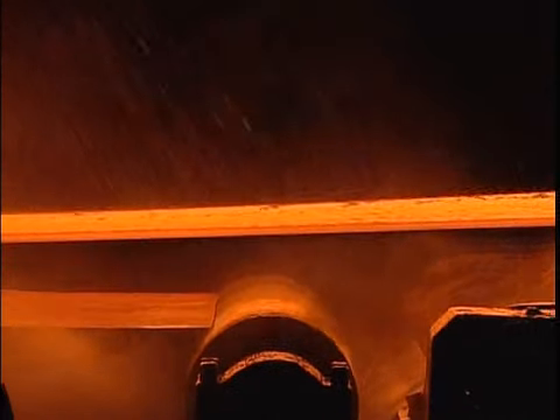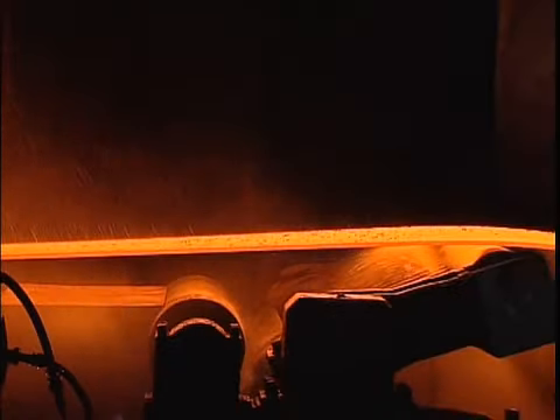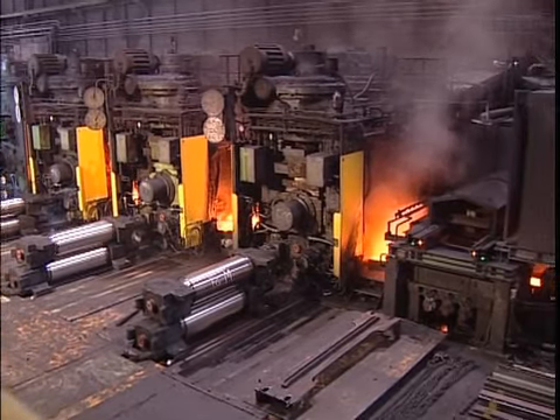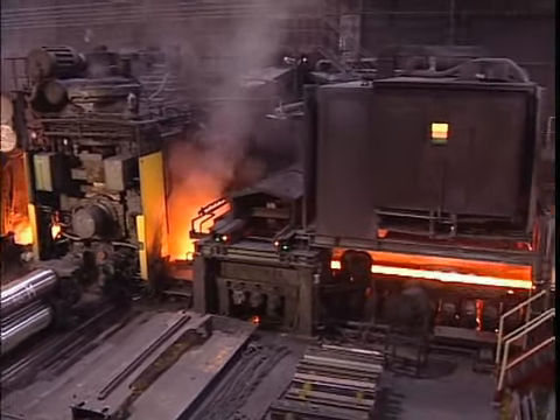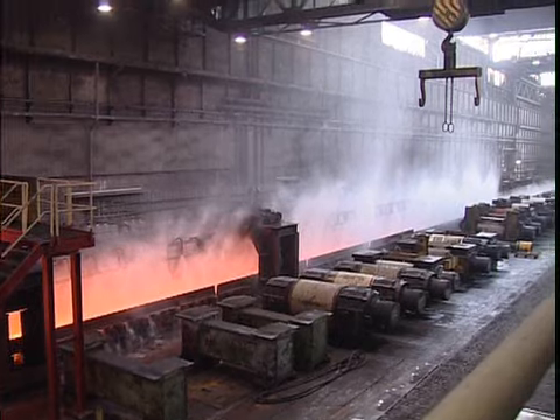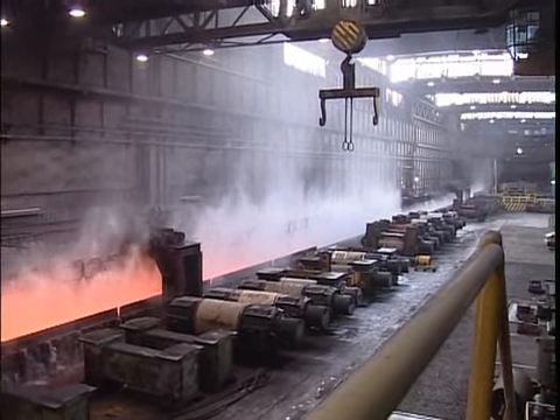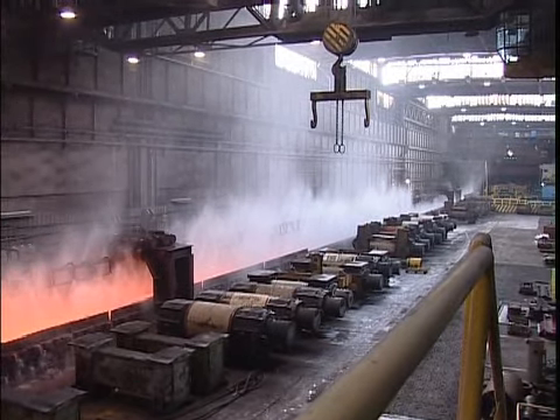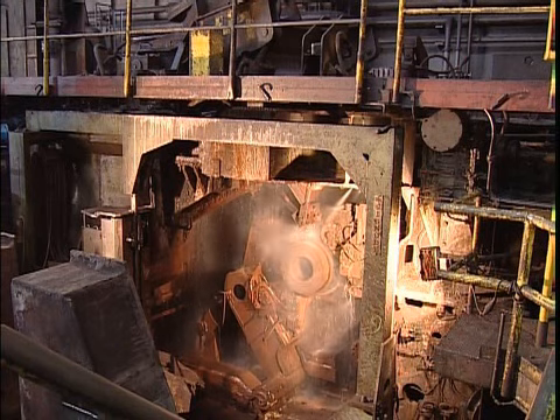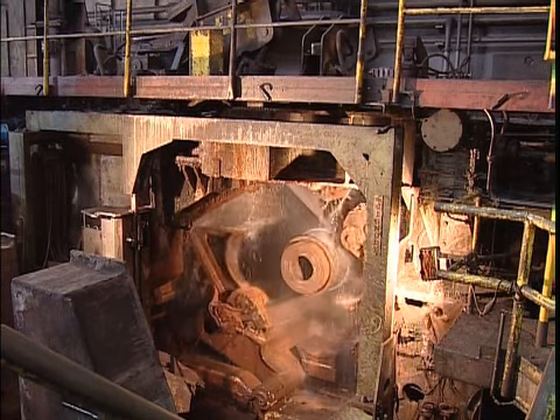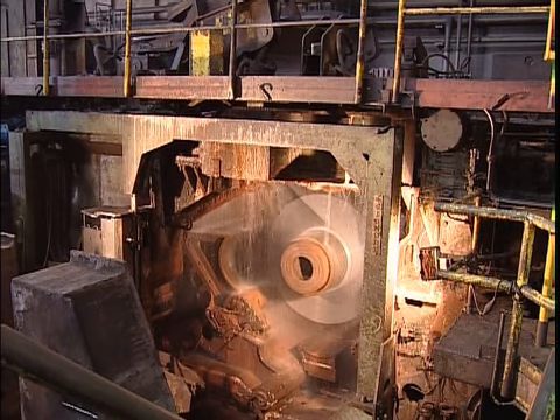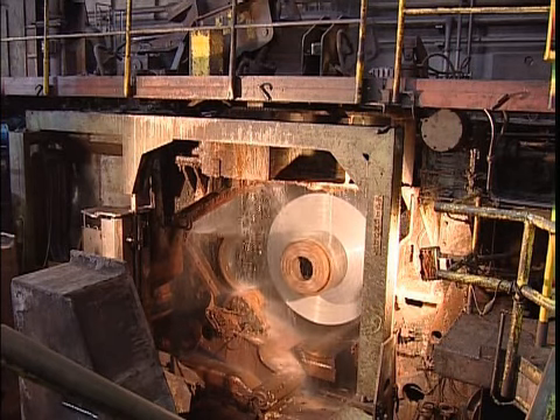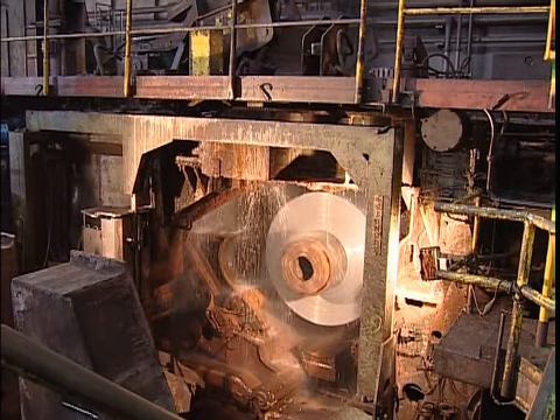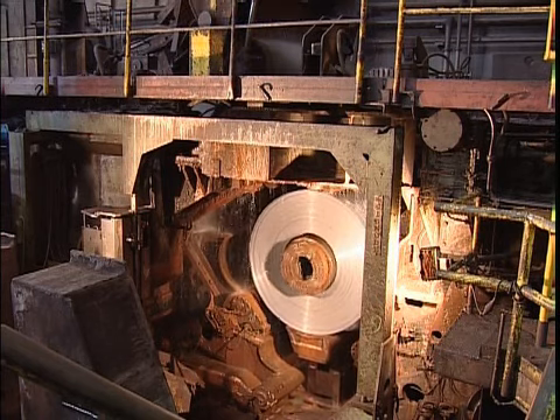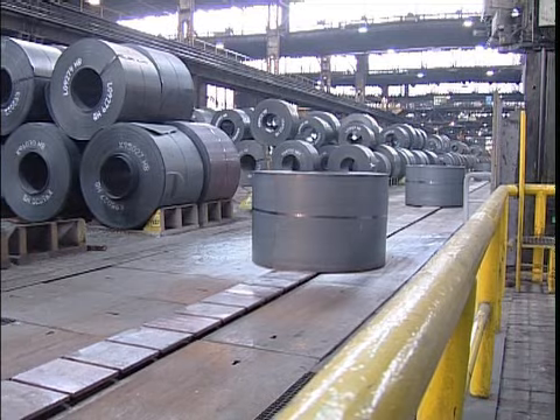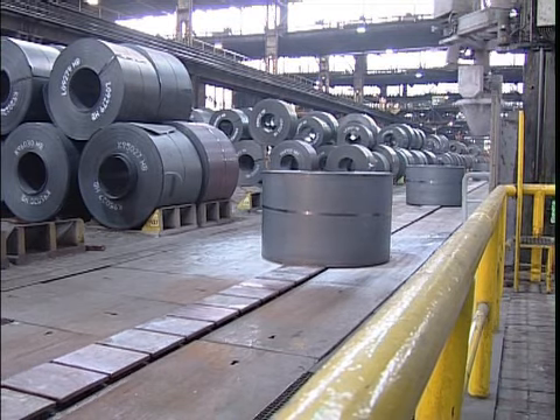The following 7-stand finishing train, with a drive of 50,000 horsepower, reduces the material further down to 2.3 millimeters. After the cooling section, the hot-rolled strip is coiled at a speed of more than 13 meters per second. ThyssenKrupp Stahl produces and supplies more than 300,000 tons of hot-rolled coils per year, dedicated to the production of grain-oriented electrical steel.